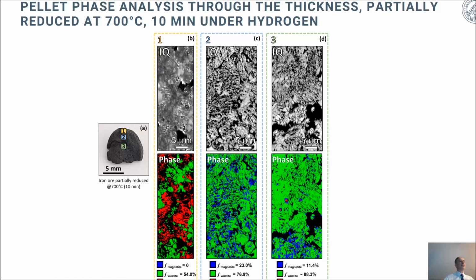What is also very interesting is, if you do not only look at the very fine scale, but take one step back and look at the gradients of the reduction kinetics and the porosity through the thickness of the pellet. When we show that here in terms of a pellet which has been cut through and follow these three positions from the outside towards the center, then you can see how the reduction is much higher in those regions which are closer to the outside, and it's much more sluggish in those regions which are closer to the inside. So this can be explained in part by the oxygen obviously also having to take a long diffusive path outbound of the pellet, or at least towards the next available internal interfaces.